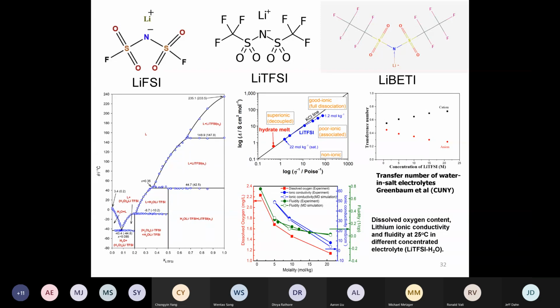So that implies that this whole system has another drawback: it doesn't have very good thermal stability. If you change the temperature a little bit, I think it will become very unstable, especially at low temperature. But the bizarre thing here is, normally in a normal electrolyte system, if we reach 5 molar or 10 molar, it will have a very high viscosity because you have a huge amount of ion pairs. But in this water-in-salt, it's very bizarre, because if you reach higher concentration, according to the Walden plot here, it actually reaches the superionic area, which means the viscosity and the conductivity are decoupled.